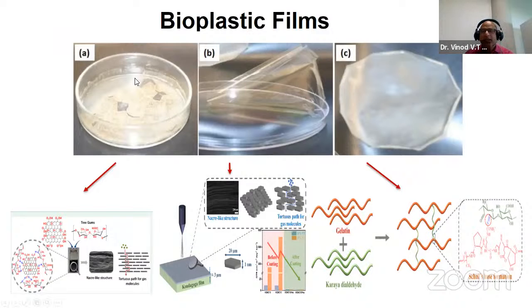As such, gums cannot be used for films because they have a very poor film formation ability. You can see they cannot make good films because of their structure and hydrophilicity. So here we use various techniques to make the films. We use chemical modifications as well as other materials like graphene oxide conjugation with the gums to give these films good mechanical and barrier properties.